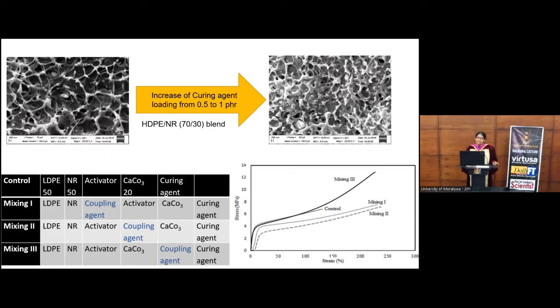This is another result of one of our research studies. If we add a small amount of curing agent, we can see coarse morphology, but by changing the loading of the curing agent, we can have the fine morphology to improve the properties that we require.